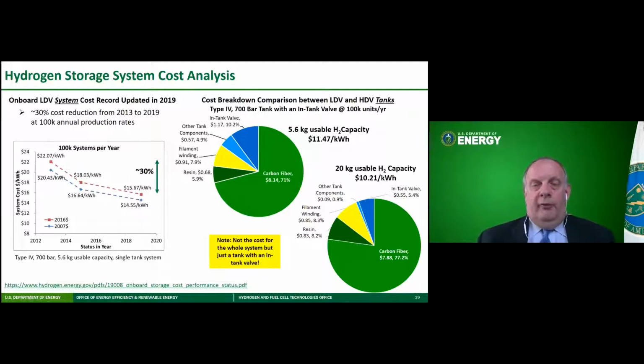However, we can take a repeat unit. This is looking at a tank that would fit behind the cab with about a 20 kilogram usable capacity. When you do the same breakdown, we see we're a little bit cheaper, about over $1 less per kilowatt hour. Carbon fiber is about 77%. The other tank components, such as the boss and the liner and the dome caps, essentially go away. But it's really the resin, the lining, and the carbon fiber that dominates.